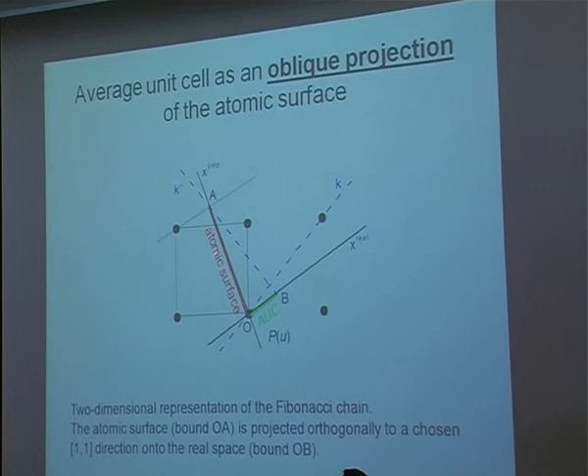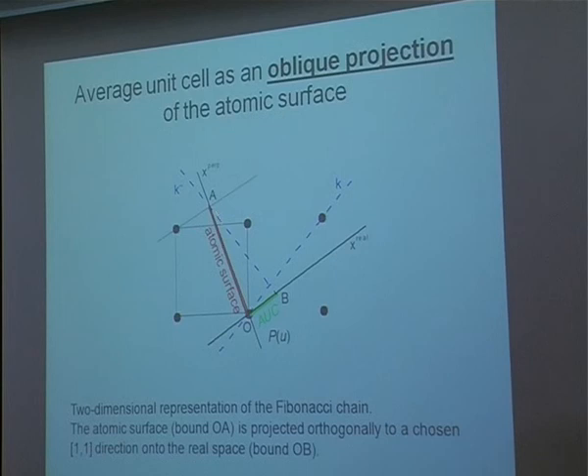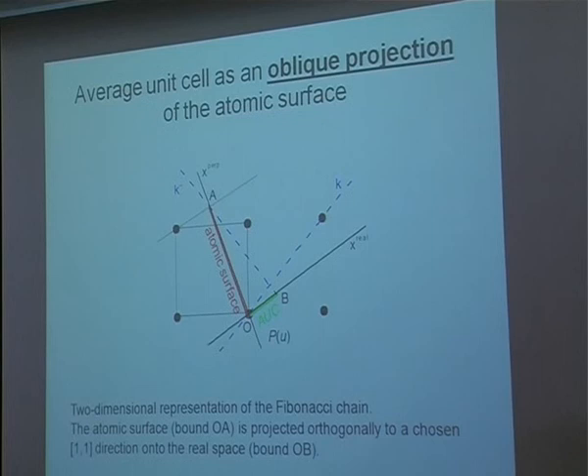So in that sense, the average unit cell is a projection of the atomic surface to physical space. We can also say that the atomic surface is an average unit cell risen up to high dimension. So if the structure can be described in high dimensions, the two approaches are completely equivalent — we are talking about the same thing. But of course there are many structures which cannot be described in high dimensions, or for some structures we would like to refine in real space rather than in high dimensions.